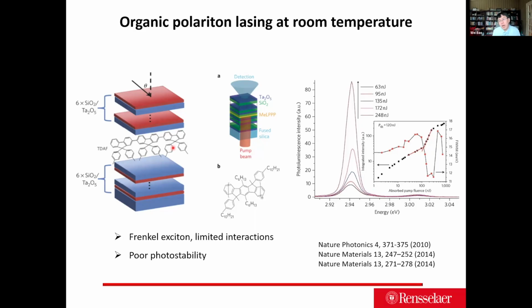The good thing is, if you have a certain defect, the organic molecules are not sensitive. For example, if you have one molecule that is burned by the laser, the system still has 99 molecules. These 99 molecules still behave like a Frenkel exciton very well. You have a quantum yield of 99%, almost not deteriorated by the burning of one molecule.